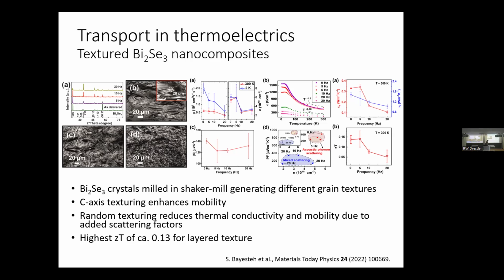This was important in its moment some years ago, because the trend back then, in the community, was to nanograin everything. Nanograin everything because you strongly reduce the thermal conductivity, and that should be better. No, sir, it's not, because you have collateral effects, and in particular in the most efficient thermoelectrics, this type of materials, that's what you don't want. You want to have a compromise between the reduction in thermal conductivity and the possible reduction in electrical conductivity.